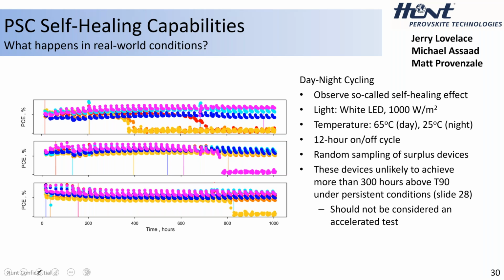What I want to highlight, we have 3 different substrates with 6 solar cells each here. And these are not special cells. These are like leftover extra ones. This is a test. I actually found these data kind of hidden yesterday when I was looking because we hadn't really been highlighting this. This was just a test we were doing on the side for fun. And it turns out it's quite remarkable because these are leftover cells we had nothing better to do with. They weren't purposed for another durability test. The better ones we make, more focused ones go into durability testing. These weren't destined for that. But if we do day-night cycling, you can see they are quite robust. They're really flat over the course of 1,000 hours.